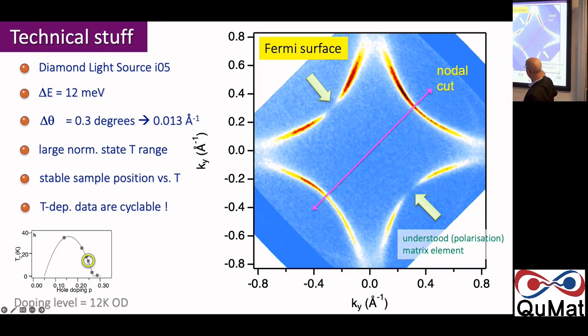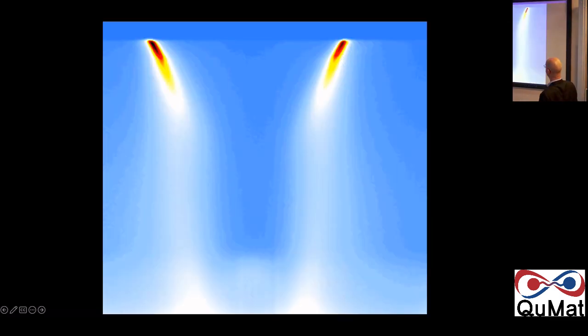So we measure very carefully, or these are the numbers for the experimentalists. We pick samples which have quite a low TC. So the highest TC is 30 Kelvin because we're interested in the normal state. If we took a high TC sample with a TC of 100 Kelvin, we could only start to measure at 110. So it's too much thermal energy. So on purpose, we're looking at low TC versions of the cuprates, so we can study the normal state even at low temperatures. Okay.